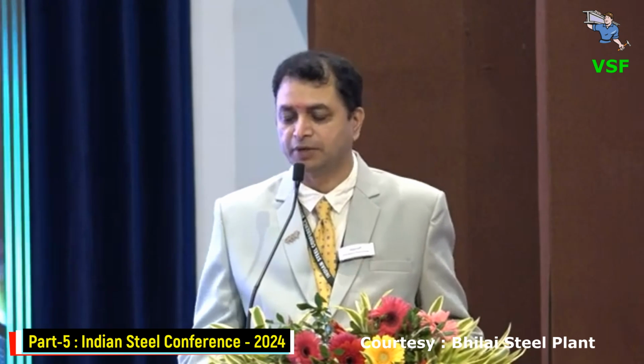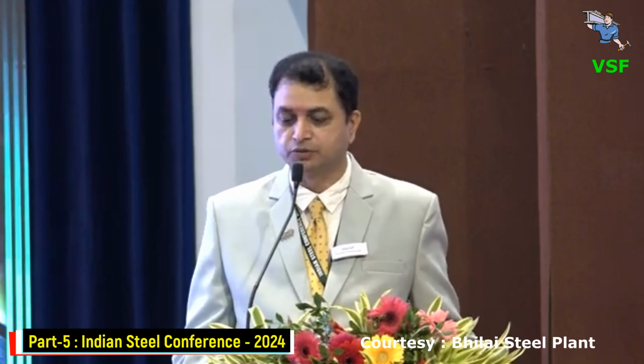And you can see in the end the DRI quality, we produce DRI from 1.5 to 5% carbon. 5% carbon is just a replacement to the hot metal which we are getting from the blast furnace, with more than 4%. And whatever carbon we get is in an iron carbide form. So this is basically the scheme of our Energiron DRI making. The aim is to reduce the carbon footprint.